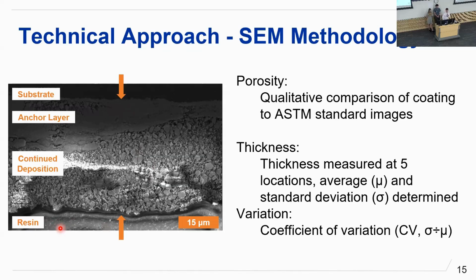pre-processing step for SEM. So porosity, we did a qualitative comparison of coating to the ASTM standard that I just mentioned. And thickness, we took 5 thickness measurements at 5 different locations on this SEM image. We took the average and the standard deviation. And then finally, we calculated the coefficient of variation for thickness, which is standard deviation divided by mean.